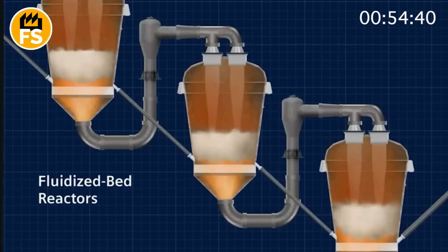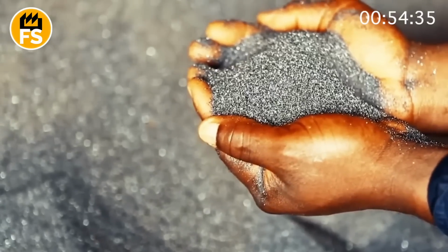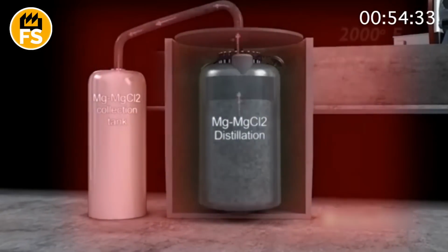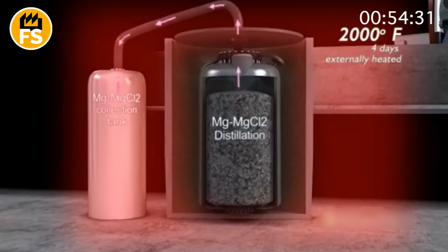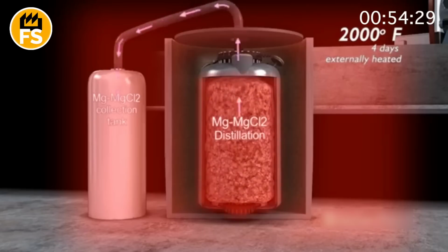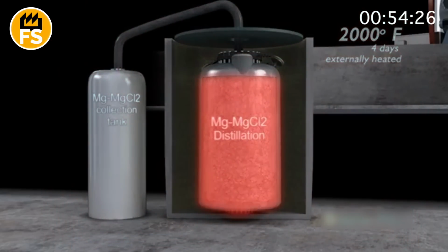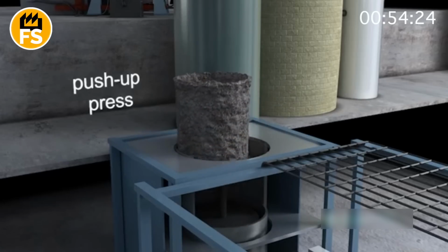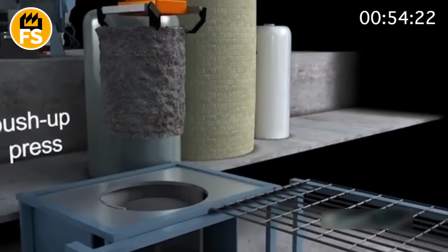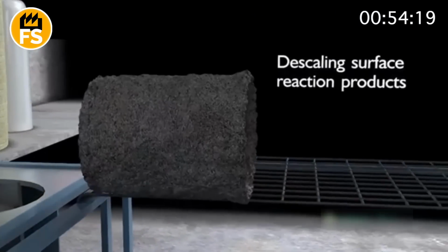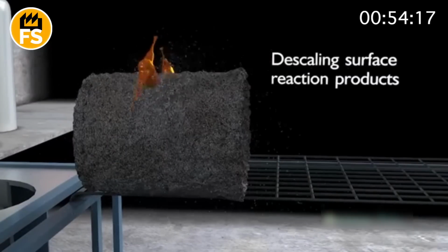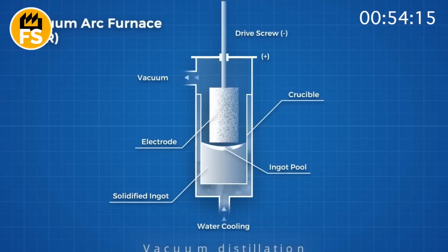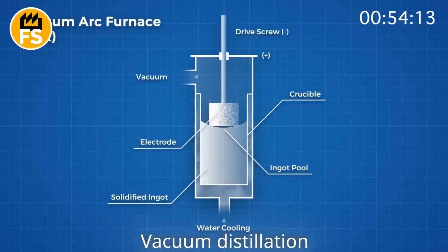The next key stage is the reduction of titanium tetrachloride to metallic titanium. The most common industrial method is the Kroll process, in which titanium tetrachloride reacts with magnesium in a vacuum chamber at a high temperature. As a result, spongy titanium is formed, a porous metal powder that contains impurities of magnesium and magnesium chlorides. This reaction mass is subjected to vacuum distillation to remove impurities, after which the spongy titanium is pressed and remelted into solid ingots or slabs.